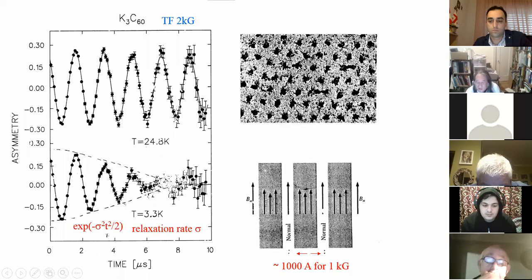Okay, and this flux vortex structure is something like a mesoscopic structure, because each of the flux vortex carries something called flux quanta. And so applying a given field immediately would allow us to estimate the size of this sort of ring size. And if we apply 1 kilogauss, this interval of adjacent flux is something like 1,000 angstroms. So this is a mesoscopic structure.